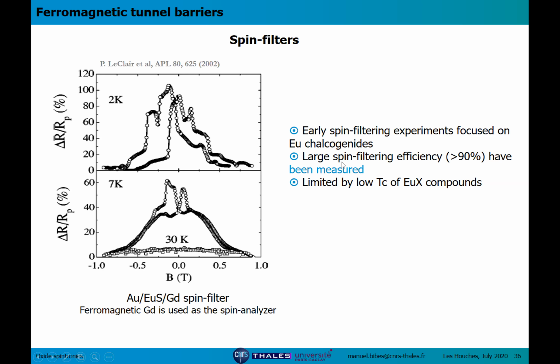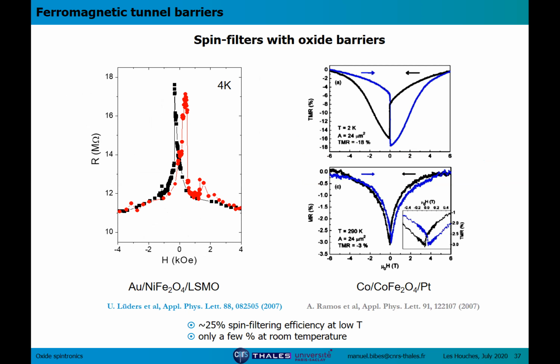So this is nice, but these europium oxide, europium chalcogenide compounds are a bit difficult to work with because they are not very compatible with many other compounds, and they have low TC. So in oxides, there's a number of ferromagnets and ferrimagnets with high TCs, and several groups, including ourselves, started to work on spinel ferrites, which are ferrimagnetic insulators with a TC of about 800 Kelvin, as spin filter barriers.